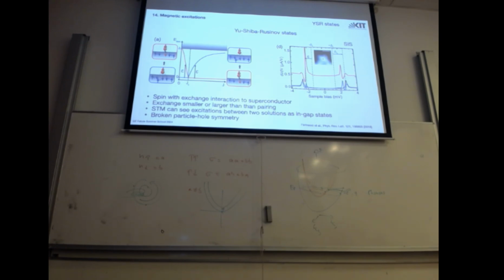There are two solutions to this problem. Either the exchange of my localized spin in contact with the superconductor breaks the Cooper pair, and I have now, for example, antiferromagnetic coupling of two electrons, one localized on my impurity, one in the superconductor, or the exchange is weak, and I just keep my Cooper pairs, and they are in some kind of effective magnetic field, which is not enough to break them. So these are two solutions that can happen. Both solutions have an energy.